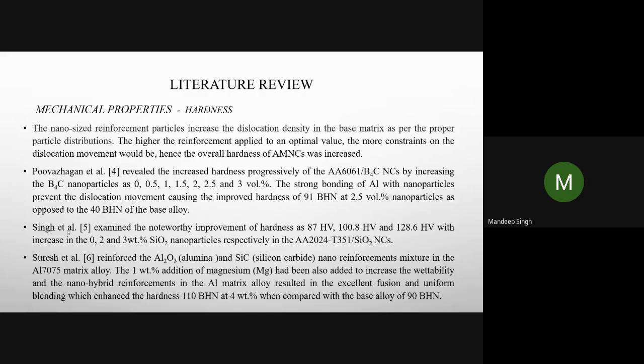Next, Singh et al. examined the noteworthy improvement of hardness as 87 Vickers hardness, 100.8 Vickers hardness, and 128.6 Vickers hardness with increase in the 0, 2, and 3 weight percent silicon dioxide nanoparticle respectively in the AMNCs. So the strong interfacial bonding between the nanoparticles and the matrix gives the apparent wettability and the uniformity of nanoparticles in the matrix, which was accountable for the hardness of the AMNCs.